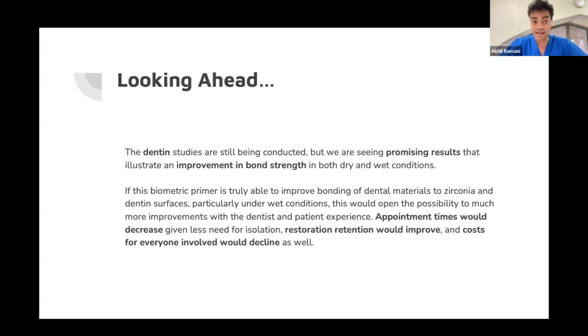And so just looking ahead, the dentin studies are still being conducted, but thus far we are seeing very promising results that illustrate an improvement in bond strength in both dry and wet conditions. And then, as mentioned earlier, this is actually truly able to improve the bonding of the dental materials such as zirconia and dentin in wet conditions, that would open the possibility to a plethora of more improvements in the dentist and patient experience. Thank you.